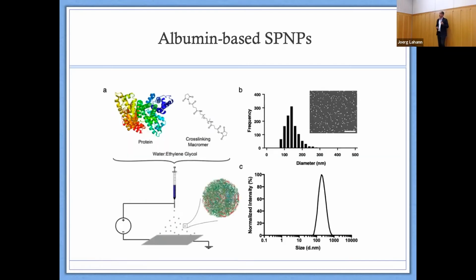Okay, so coming back, I told you leading up to this, we actually now move from the synthetic polymer, such as the polyester that I used here, which is an FDA-approved polyester. So that's a nice thing. But we now use proteins as building blocks. So it's a little bit like Abraxane, but the difference between Abraxane and something like this is that Abraxane is only physically cross-linked. So the moment this gets into the blood, it falls apart. Whereas here, we chemically stabilize it. So the particles themselves are much more stable. But then when they get to the liver, you still have proteolytic cleavage of the protein part of the particle, and you have very rapid liver clearance, right?